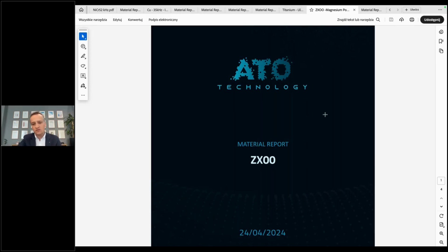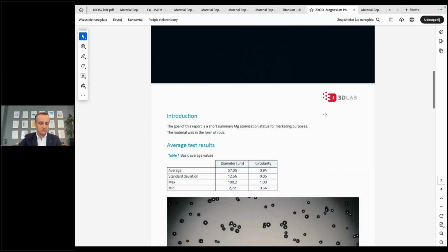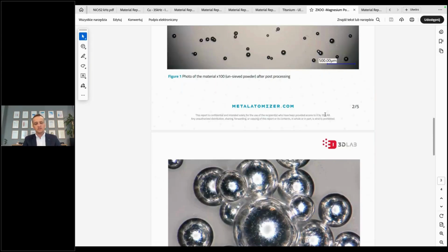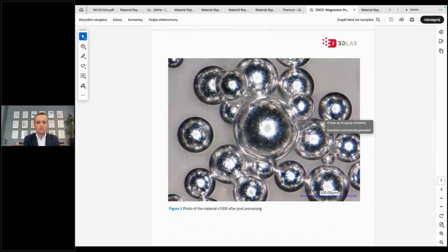So we atomized for them highly medical grade magnesium like ZX00 or WE43, and we achieved great results with this powder. The sphericity was great, the flowability much better compared to classic gas atomizers, but the most important fact, especially with magnesium, which is a very reactive material, is that we achieved a very safe process with a very narrow particle size distribution, and we kept the quality of the material in terms of the chemical composition.